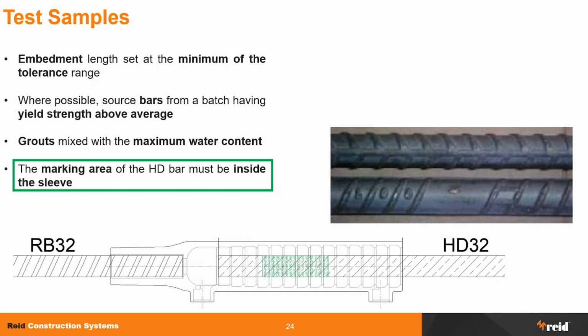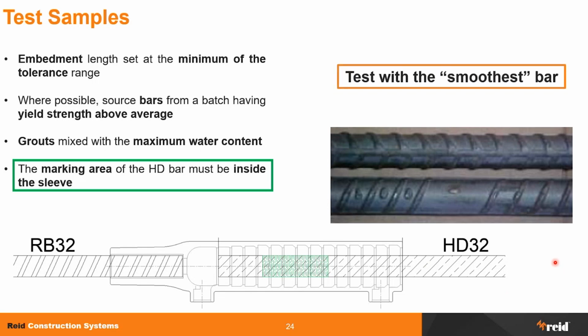And also we noticed that for the bars manufactured by Pacific Steel, coincidentally the same manufacturer of ReidBar, the marking of the 500 grade bars is missing. The marking area is missing a couple of ribs. So what we did, we agreed on testing this, which is the smoothest portion of the bar, inside the sleeve. So we included this area inside the sleeve.